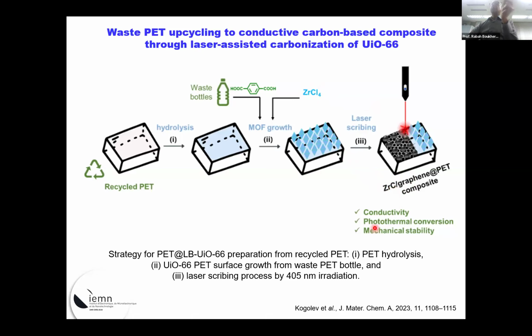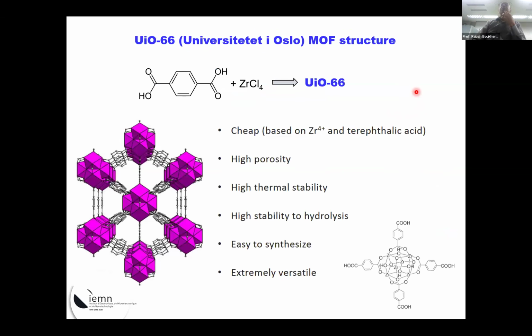We didn't do the measurements for the supercapacitors, but I will show you that it's a very nicely conducting material. And one other feature of this work: instead of using a CO2 laser, here we used an LED laser because, again, it's very cheap and small. You don't need too much infrastructure, and the investment is just about 50 to 60 euros. Of course, you don't have the control you have with the CO2 laser, but you can do quite enough things at the lab scale.